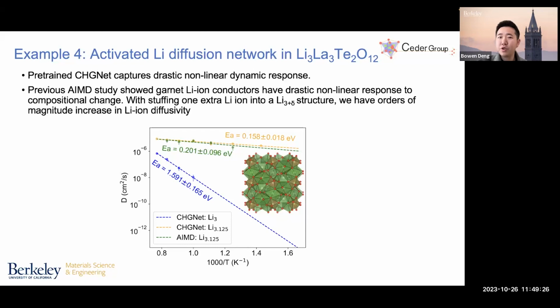And the last example I want to show today is the activated lithium diffusion network in lithium garnet. In this example, we show that the pretrained CHGNet, without any additional data in this chemistry, can capture the drastic nonlinear dynamic response that happens within the system. Previous AIMD studies show that garnet lithium ion conductors have a drastic nonlinear response to compositional change. With stuffing one extra lithium into the Li3+δ structure, we have an orders of magnitude increase in lithium ion diffusivity.